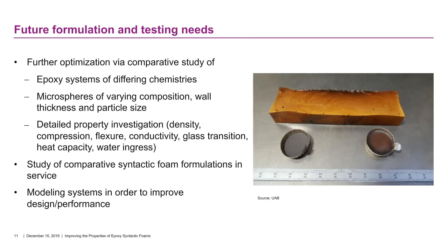So all of the raw materials obviously can be investigated, and that's something that we will start to look at in the months ahead. The phase 2 and the phase 3 will come later on once we have a much stronger grip on the variables and how they are driving the different levels of performance for us. So far, samples that we have made, here's an example of a loaf of syntactic foam which was mass cast. These samples are being produced for us, and they are of very good quality, extremely low, insignificant porosity. Very good examples which we can use to generate a much wider data set, which will further support the claims that we're making.